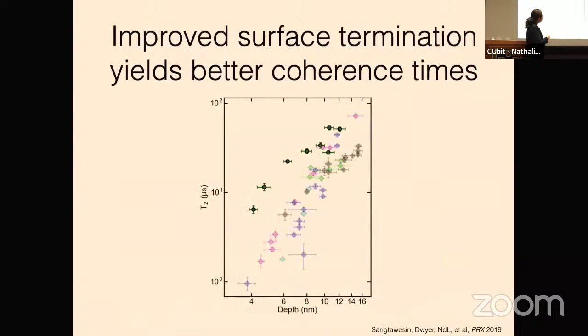Okay, the punchline is that by doing a lot of this work, we're able to extend the coherence time of shallow NV centers by around an order of magnitude. So all of the points that I showed you are here sort of grayed out. And then now with our best processing, we can get to 5 nanometers from the surface with 10 microsecond coherence times. And then importantly, we can dynamically decouple out to something like 200 microseconds. So we now have very nice coherent shallow NV centers.